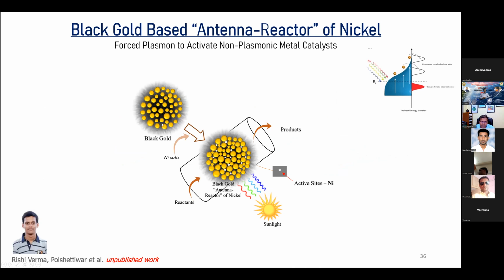The black gold is loaded with a nickel site, so now you have gold and nickel sites. Electron is generated in the black gold and then it goes to the nickel, and nickel becomes my reactor. The antenna is the black gold, which takes all the photons and gives the electron to the nickel, and nickel becomes catalytic. Nickel takes the CO2, nickel takes the hydrogen, and with this electron reacts CO2 with hydrogen to get different products like CO, methane, and other products.